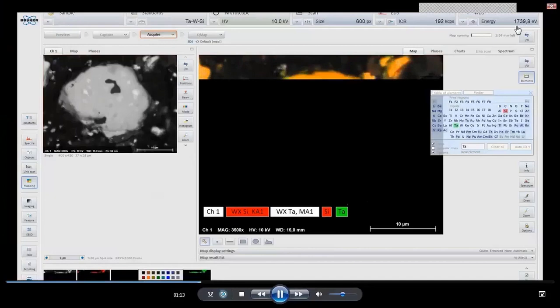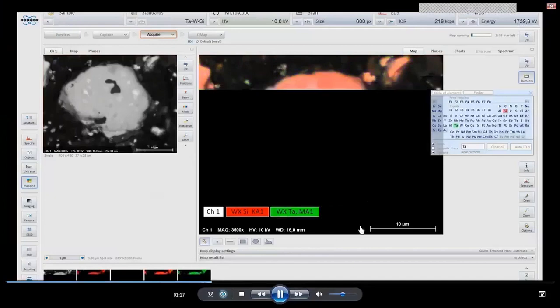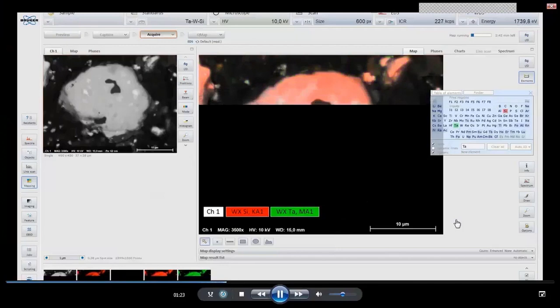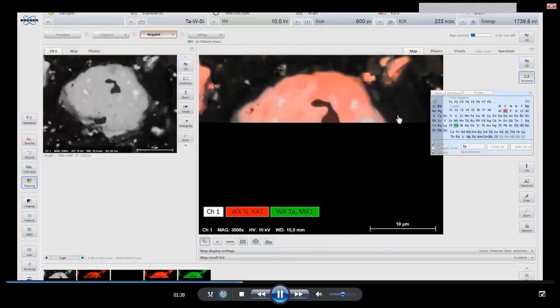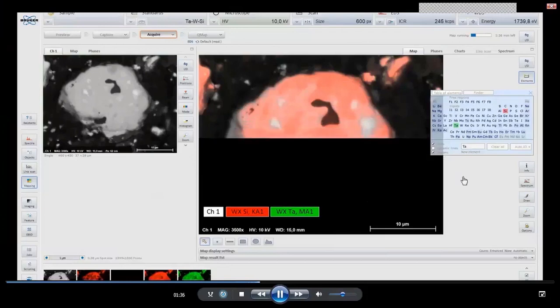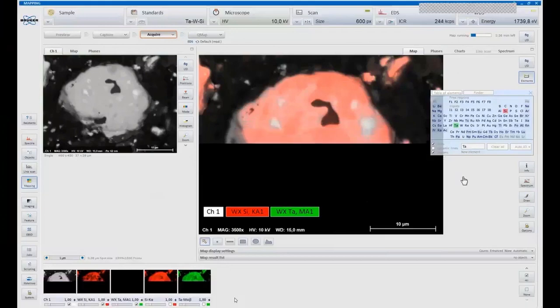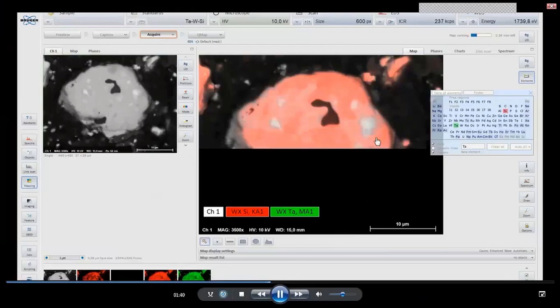This is the energy of the silicon. We are mapping EDS together with the WDS. We will only show WDS at the moment. Silicon is mapped with red colors, and we are proceeding with a slow speed, set to about 1 minute per frame. So we are mapping now for the silicon.